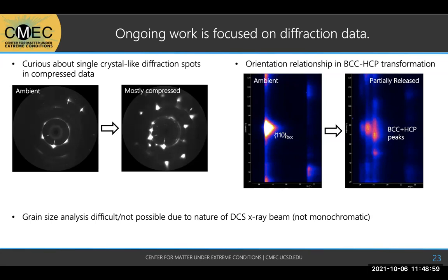Another portion is the orientation relationship between the BCC and the HCP transformation. So both the forward and the reverse versions. And so you have this one peak that breaks up into the 3 HCP peaks. And so that's something I also want to be able to determine, because there's a lot of papers out there that do look at this orientation relationship. And so it'd be nice to be able to agree with those.